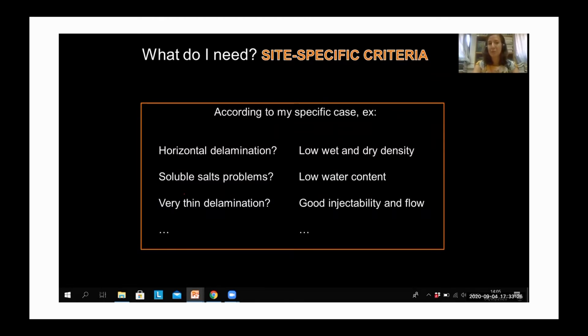Do I have a very thin delamination? Well, in that case, as you can imagine, I have a very thin gap, and so I need a grout which is very fluid. So I will need a very good injectability and a very good flow. So as you can imagine, every case is different. And so every time I need to set these site-specific performance criteria to lead the formulation of the grout in the, let's say, right direction.